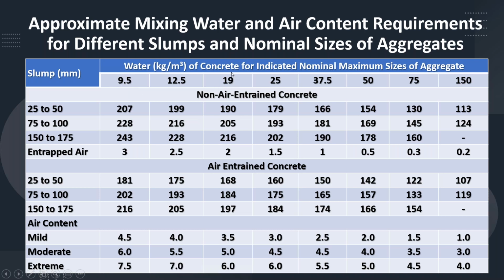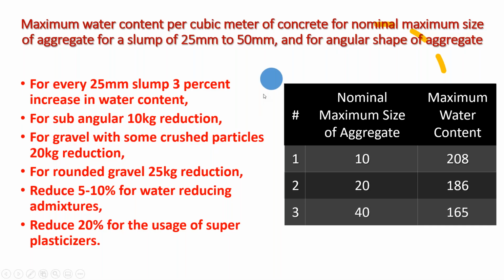You see this particular size, 19 mm. We have approximated it to 20 mm. You see this size, 37.5. We have approximated it to 40 mm. We picked up only these values, because the entire method we cannot copy. We have picked up only these particular values, and we have shown them in our IS code 10262. Then you can see 10 mm, 20 mm, and 40 mm, and this is the maximum water content. You can see the title of this table: the maximum water content per cubic meter of concrete for nominal maximum size of aggregate, for a slump of 25 to 50 mm, for angular shape aggregate, of course.